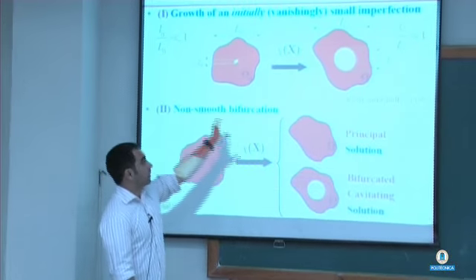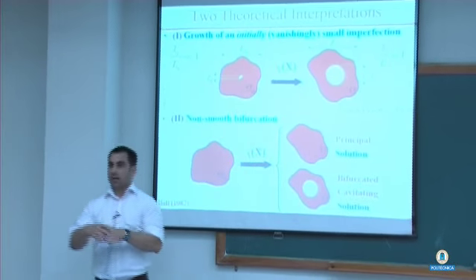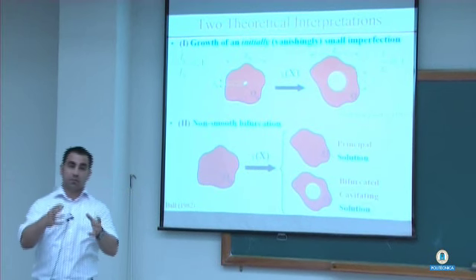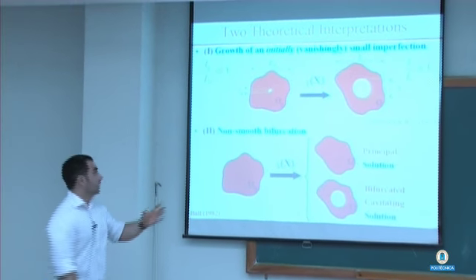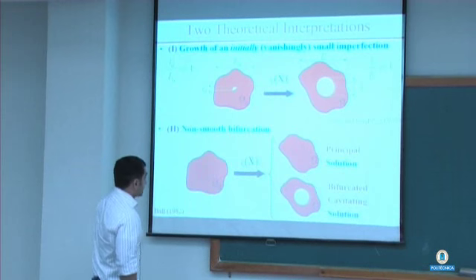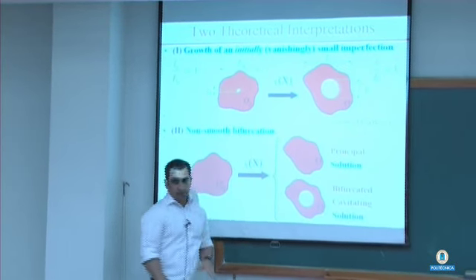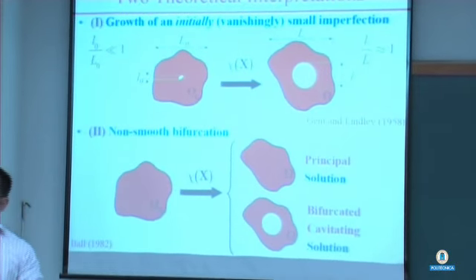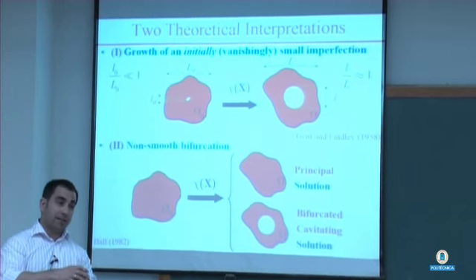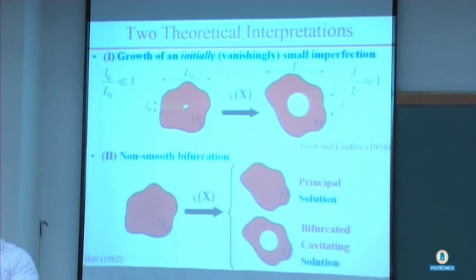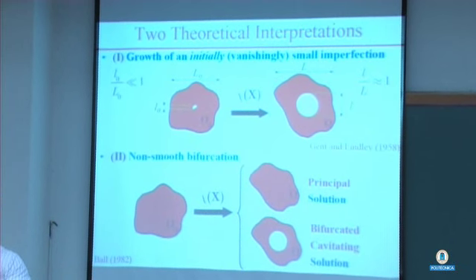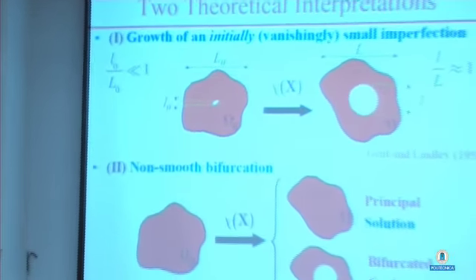And what is cavitation? Basically, well, you have a very, very tiny hole, and cavitation corresponds to the event when this tiny hole becomes of finite size. At some critical deformation, it becomes of finite size, right? So this is the growth of an imperfection. And of course, you already know that in classical linear elasticity, this cannot happen, right? If you have a hole of infinitesimal size, the hole in the deformed configuration will be also of infinitesimal size because it has to go linear with applied boundary conditions. But here we're interested in soft materials. This is a nonlinear material, and this certainly can happen.